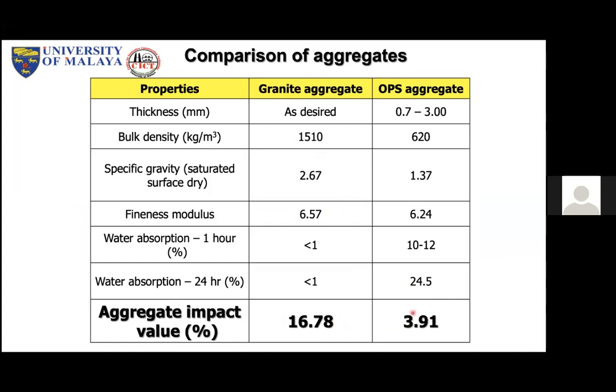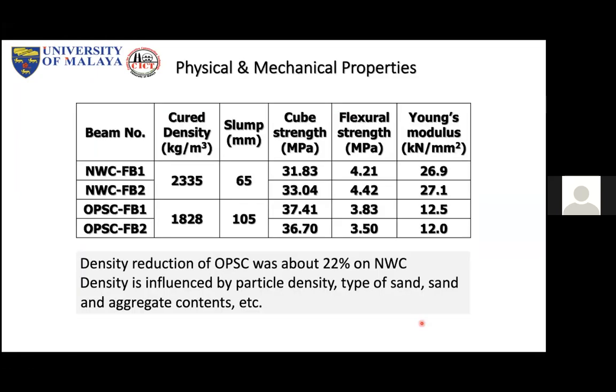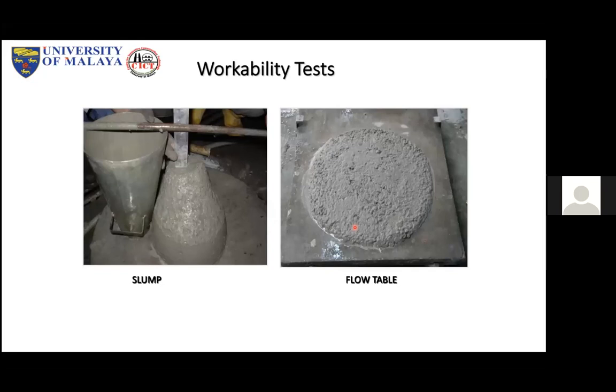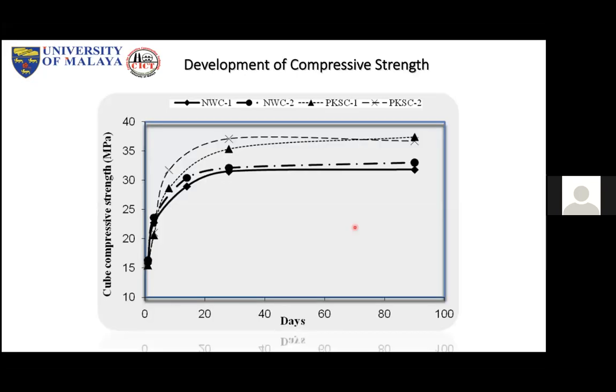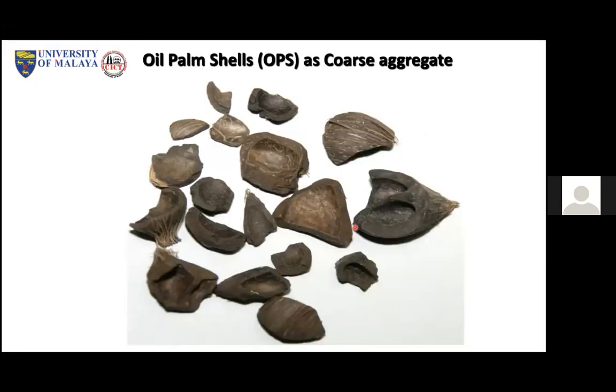So we tried to use this property, and we did manufacture concrete. You see the density between this and this normal weight concrete. The density is around 2,300. This lightweight concrete, shell concrete, we manufactured with 1,800. With the compressive strength comparable, even though this is 30 and this is 37, this is likely higher because we use silica fume, and we managed to get this compressive strength for manufacturing the concrete. So we see the slump values, compressive strength, and this is the shell configuration.